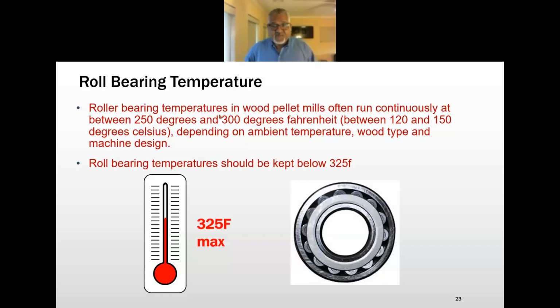Roller bearing temperatures in wood pellet mills typically run between 250 and 300 degrees Fahrenheit. For an international audience, that's 120 to 150 degrees Celsius. It depends on ambient temperature, wood type, and machine design. It just depends on many different factors that affect pellet mill temperatures. But these temperatures should be kept below 325 Fahrenheit to protect the metallurgy of the bearings and the roll shells.